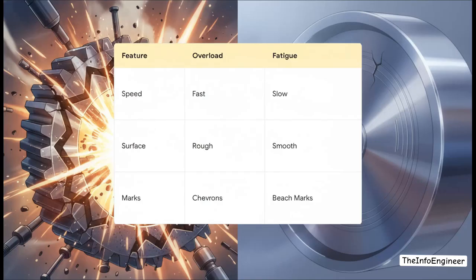During this autopsy, the very first thing we need to do is distinguish between an acute overload and a slow fatigue failure. An overload failure, it's fast, it's forceful, and it's obvious. If a machine jammed or took a massive impact, you'll see a fracture face that is rough, dimpled, and fibrous. You'll often even see chevron patterns pointing directly back to where the break started. Fatigue, on the other hand, is a slow burn. Because the crack faces rub together over thousands of cycles before the final break, the fatigue zone will actually look incredibly smooth, polished, and sometimes even discolored from fretting.